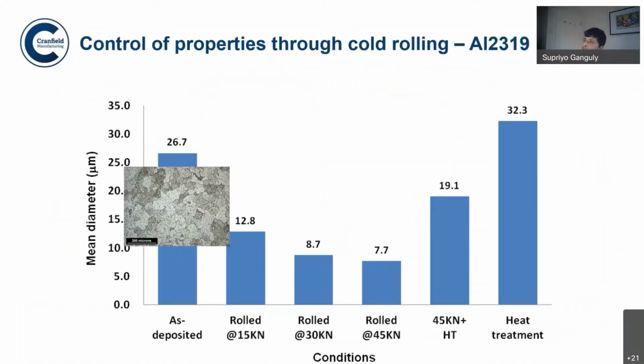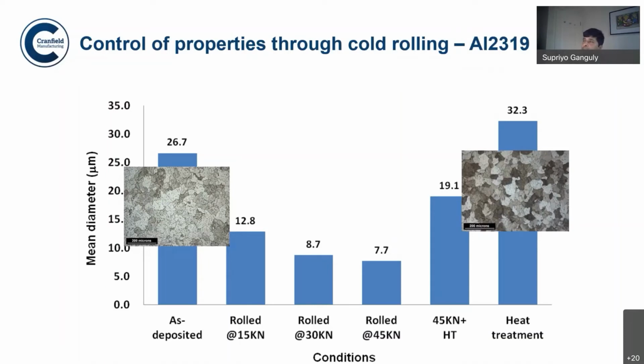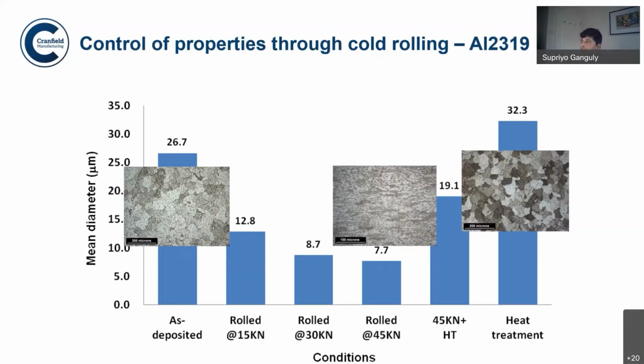So, control of properties through rolling. Aluminum is also one of the major candidates for cold rolling, and you can see here, in the as-deposited condition, how the size of the grains, actually the mean diameter of the grains, is changing. You can see that the nature of the grains was changing, with lowering of the texture and lowering of anisotropy. These are the different grain structures that you can obtain.